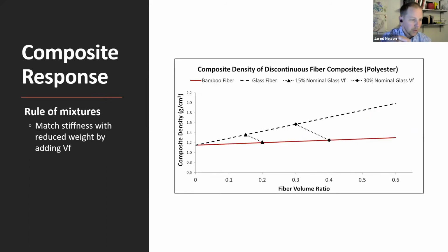If we go ahead and do a similar analysis that looks at the composite density, we can also see that with these same analogies, even though we're increasing the amount of fiber, we are dropping weight. We are less dense by going to bamboo at this increased level in both cases. Pretty significantly, our composite density goes from almost 1.4 down to just under 1.2, and similarly from about 1.6 down to 1.2, in grams per cubic centimeter. So again, we are achieving similar stiffness and we're dropping weight significantly.